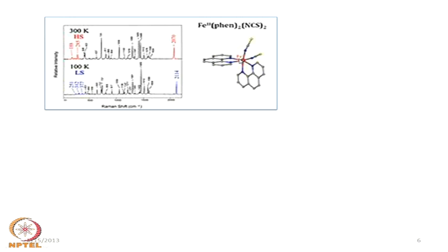So, as we move to the high spin, the Eg levels are getting occupied. The interaction of that Eg electron with our NCS ligands is different, which affects the stretching frequency. Some of the electronic charge is being pushed to the orbitals of the thiocyanate groups, and that electron push can modify the corresponding stretching frequencies of these thiocyanate groups.